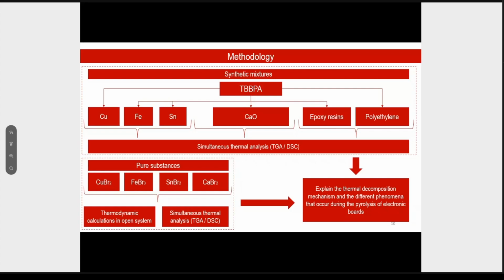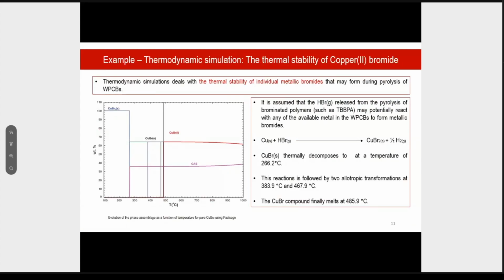So we compare the synthetic mixture and the product of the synthetic mixture using TGA DSC and the brominated metals, to be able at the end to explain the thermal decomposition mechanism of the printed circuit board. One of the examples that we can see here is using the thermodynamic simulation using FactSage to study the thermal stability of one of the brominated metals that can form, which is copper 2 bromide. As you can see here, I'm presenting a thermodynamic simulation that deals with the thermal stability of one of the metallic bromides that may form during the thermal degradation of tetrabromobisphenol A, which is copper 2 bromide.